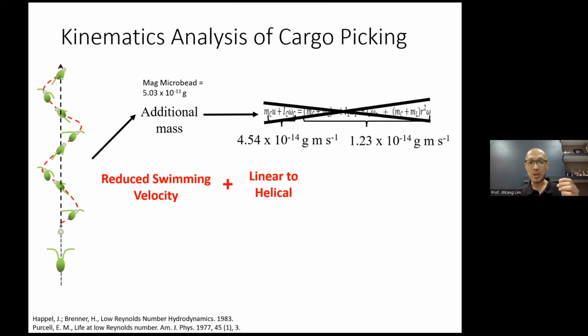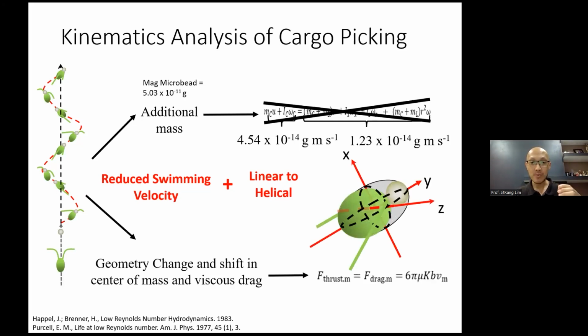And so the cell that we observe is slowed down, but the slowing down process is not because of added mass for sure, because the conservation of momentum just doesn't add up. And the other possibility is once we add the particles onto the microbot, the geometry of the whole construct actually changes quite drastically.